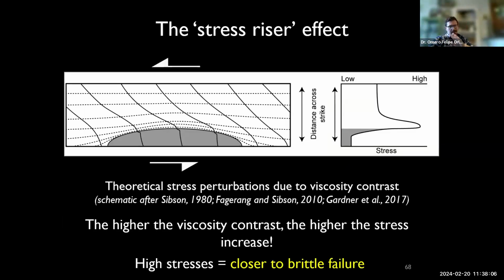And so this is an effect that has been talked about for quite a while, and it's really cool to see it in action, which is basically, right, if you have a ductile environment and everything is continuously deforming, when you have huge viscosity contrasts, you create really strong local perturbations in stress, right? Positive perturbations in stress, because you've got a squishy thing touching a thing that is not nearly as squishy, but they've got to flow past each other. And so you end up with this concentration right at the boundary.